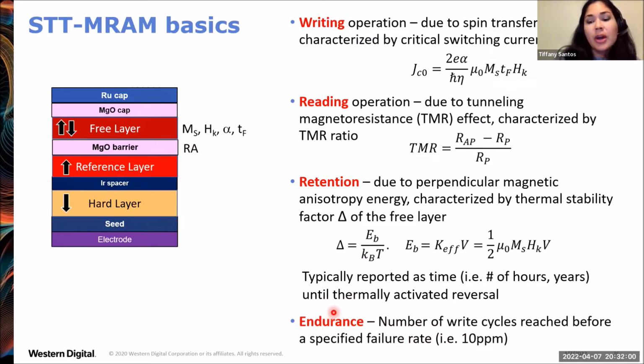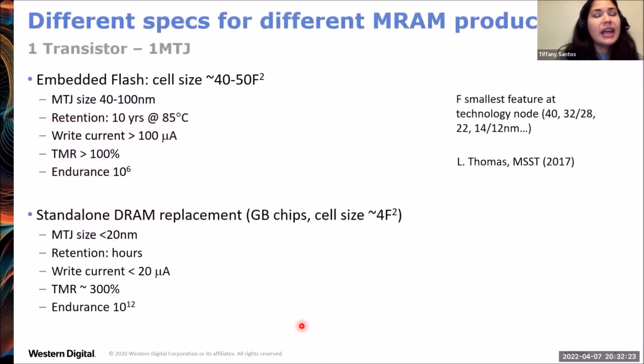Endurance is the number of write cycles reached before a specified failure rate. For example, a failure rate of 10 parts per million. So how many times can you pass a high current through the MgO tunnel barrier before you get a failure? And typically a failure is a breakdown of the barrier to a short. Okay. And different MRAM products will require a different set of specifications.